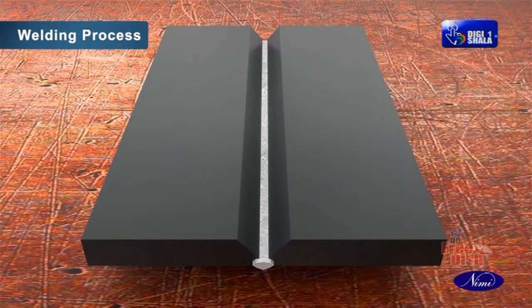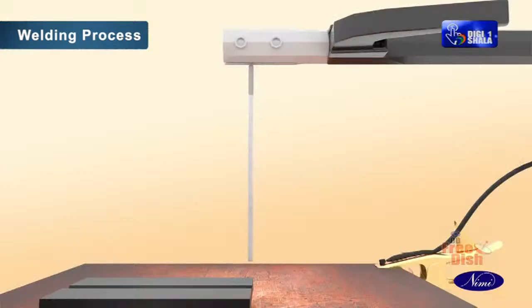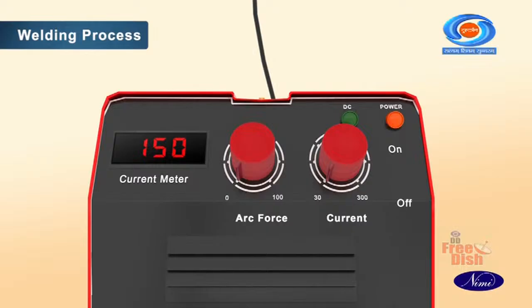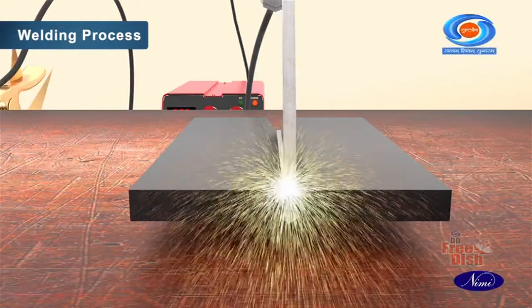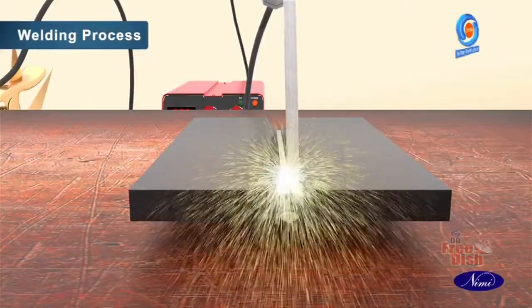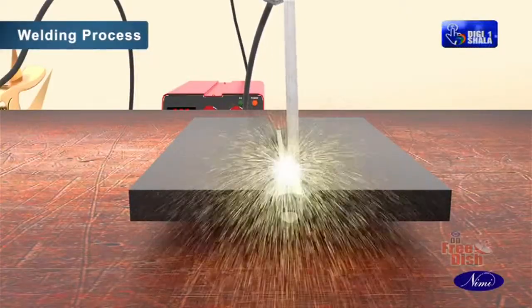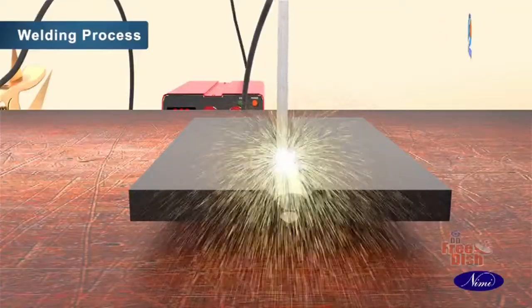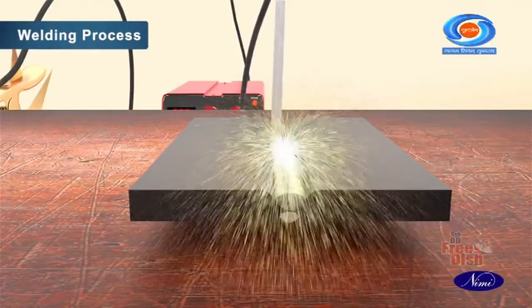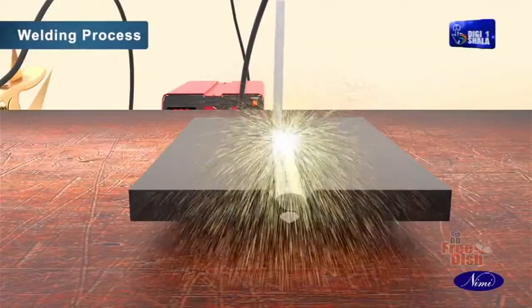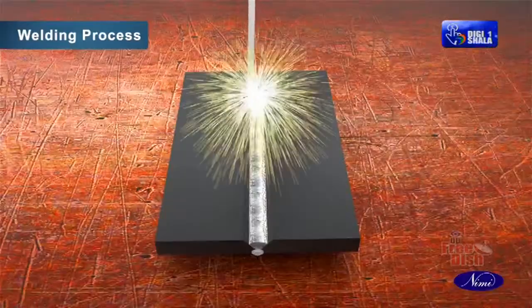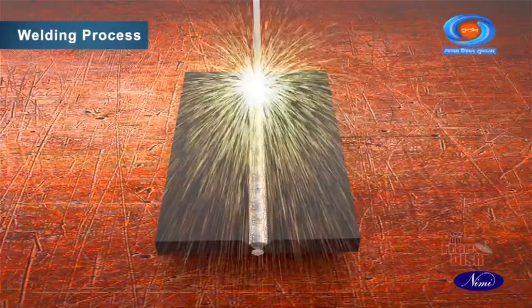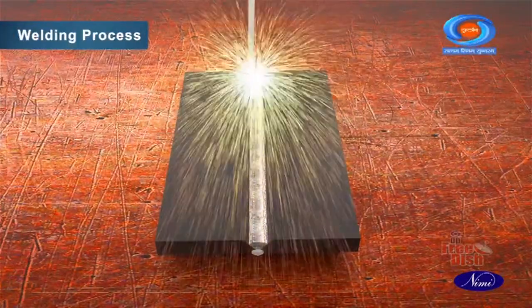Deposit the second or intermediate run using 4 mm dia medium coated electrode and with 150 to 160 amp current. Maintain short arc and proper weaving of the electrode. Avoid excessive weaving and ensure normal travel speed. Fill the crater wherever necessary and deslag.